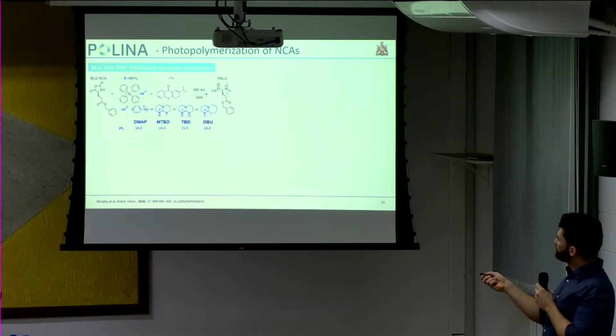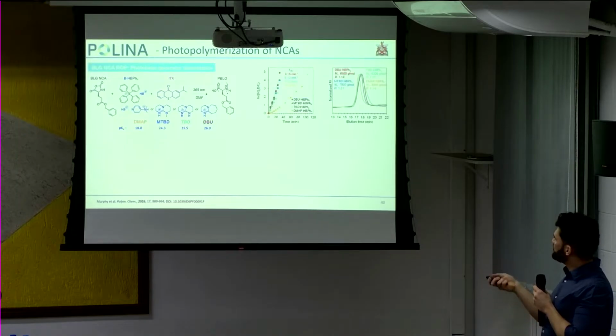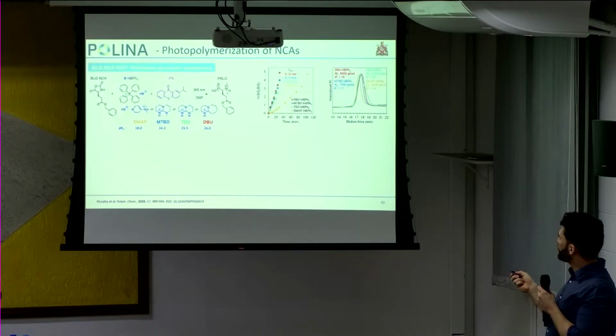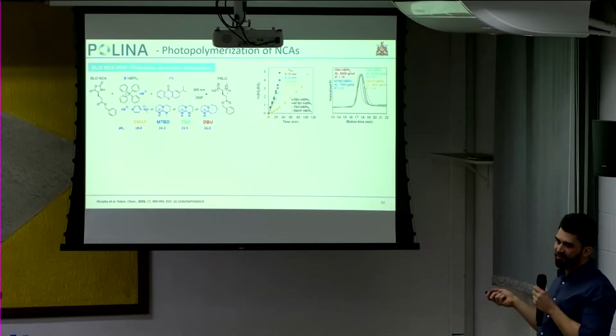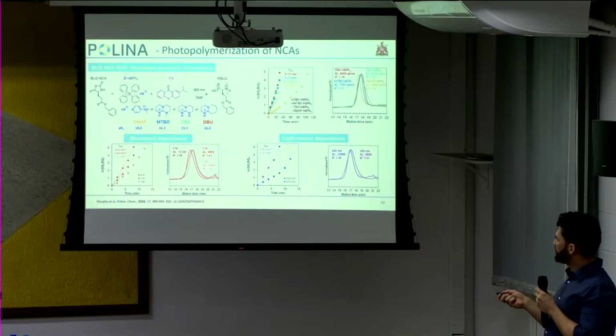And we tried different photobases with different conjugate bases, different pKa's. DBU, because it has the highest pKa, was the fastest as well. As far as molecular weight goes, it didn't change that much, but DBU was not the highest score here. It was DMAP, but DMAP is much slower, and we decided to keep the kinetics over the molecular weight, because if you're going to use it for printing, you need very fast curing. We studied the dependence of the kinetics on the monomer concentration: higher concentration, faster kinetics, and also higher molecular weight.